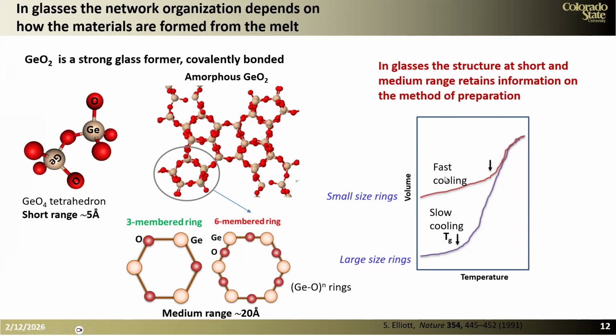And when you cool very fast, we will obtain an amorphous material, but it will be characterized by very small rings. And if we instead cool very slowly, then we will obtain large ring sizes. And this is a characteristic of a stable glass. In germania, I am going to show you that we typically observe 3-member rings and 6-member rings.